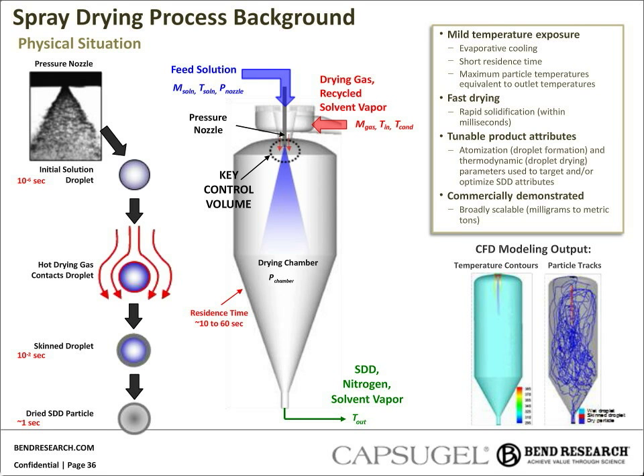So as soon as the droplets are formed, the solvent begins to evaporate, cooling the droplets to the dew point of the solvent. As the particles dry, they warm to a temperature that is equivalent to the spray drying outlet temperature as a maximum, making the spray drying process ideal for heat-sensitive actives as well.